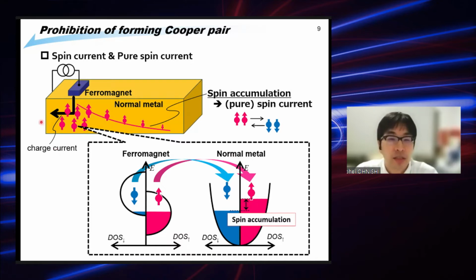Electrical spin injection can be induced by the electrical charge current. When the charge current flows from a ferromagnetic metal to a normal metal, spin accumulation is induced at the interface in the normal metal layer. This is because of the difference in the spin-dependent density of states. This is spin accumulation. This induced spin accumulation can flow in any direction in the normal metal layers.